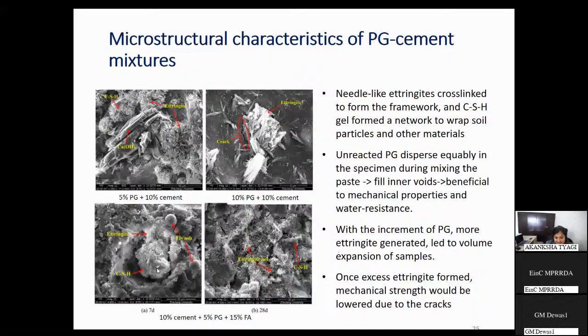I was mentioning in the last slide about the fly ash, that if you see this 10% cement plus 5% phosphor gypsum plus 15% fly ash, in 7 days you can see sphere-like particles of fly ash. They are unreacted particles. And then there is ettringite formation over the CSH gel, covering it and providing a kind of network. And up to 28 days, the fly ash, phosphor gypsum, and CSH gel have formed, and the network provides a wrapping around the soil minerals and CSH gel, and it gives good strength.